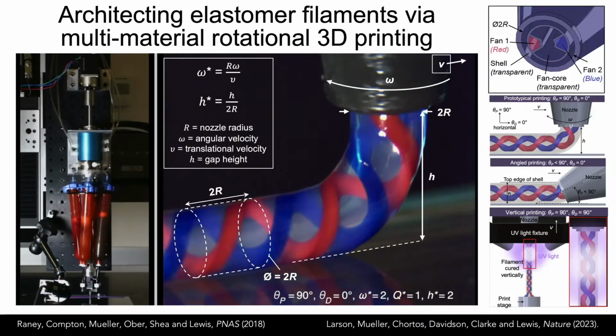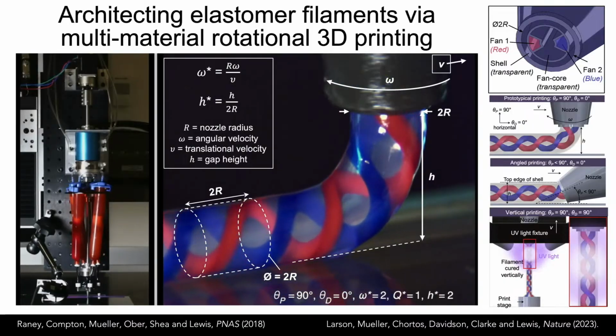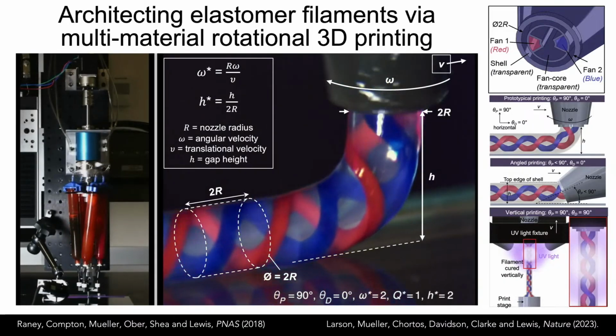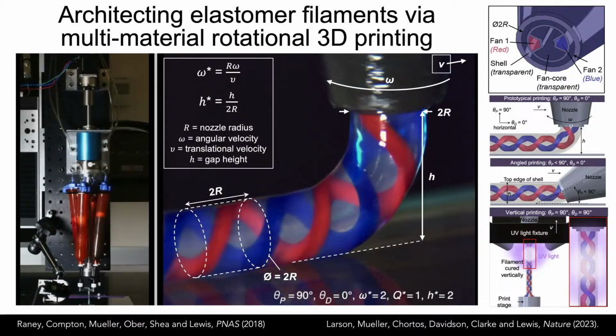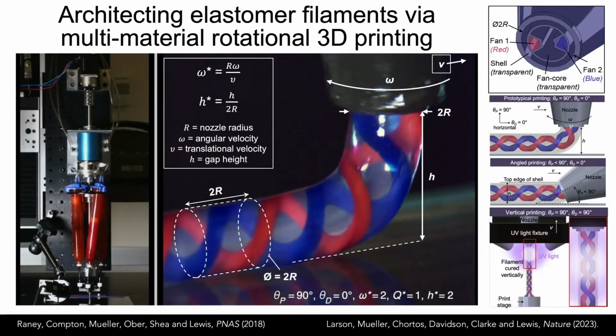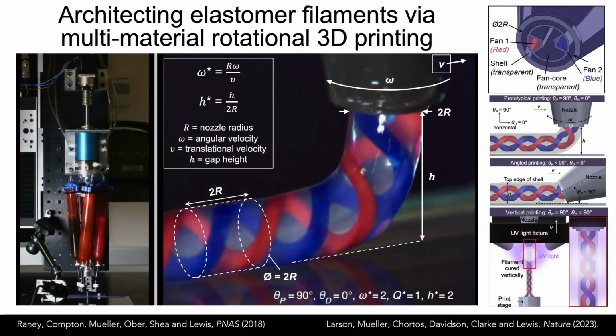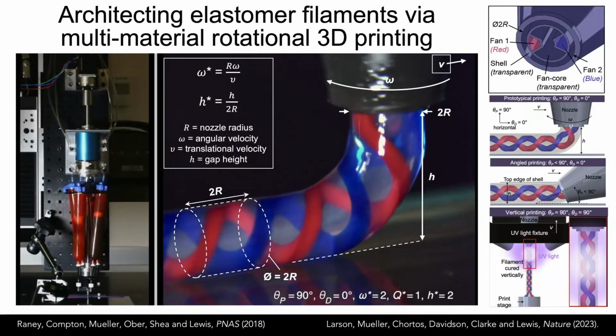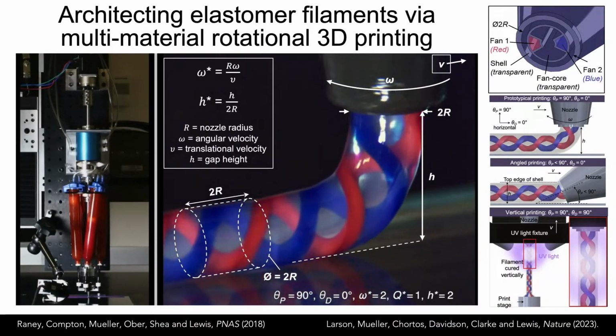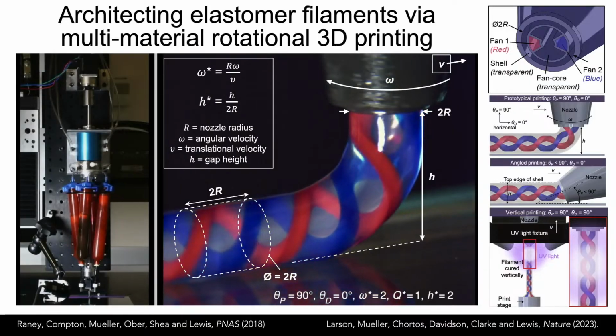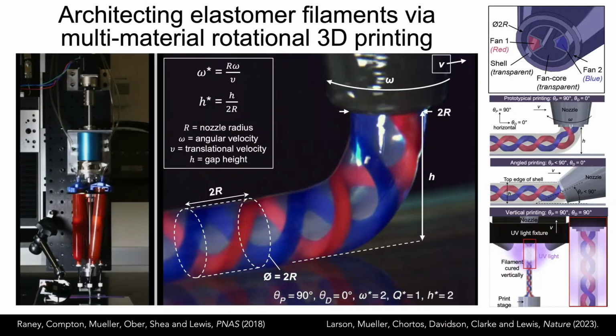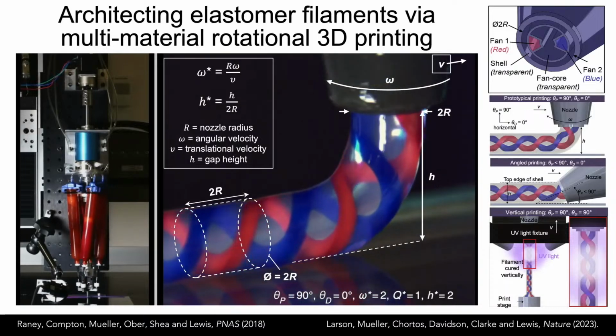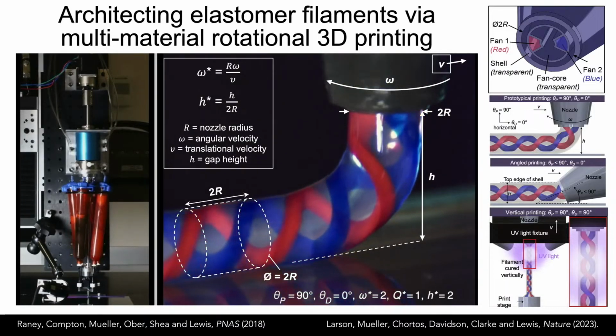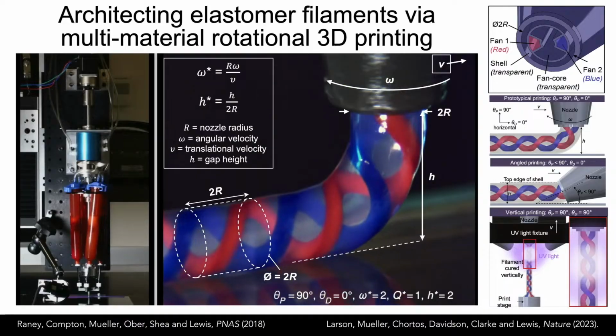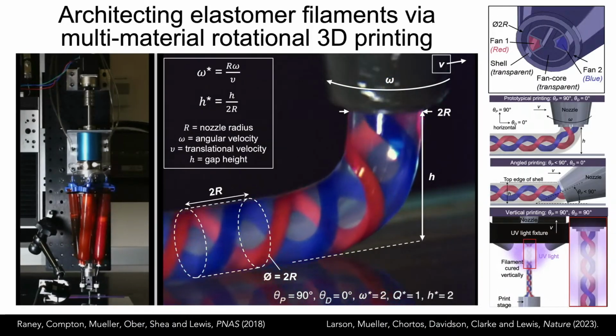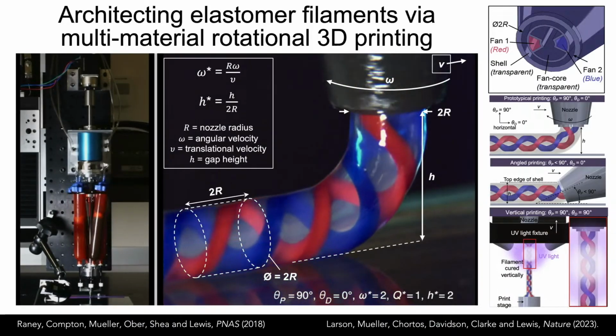Now this happens to be just a pure elastomer. These regions are simply dyed with a color so that you can see the internal structure. But we can also modulate the composition of those internal features. And we can print in our normal way where the nozzle is perpendicular to the substrate, or as we found often, we can tilt the nozzle and it actually gives a little bit better uniformity in terms of the internal architecture, or even out of plane.